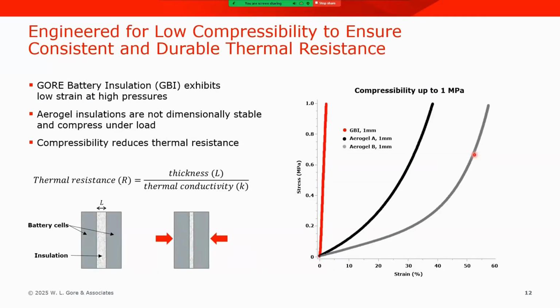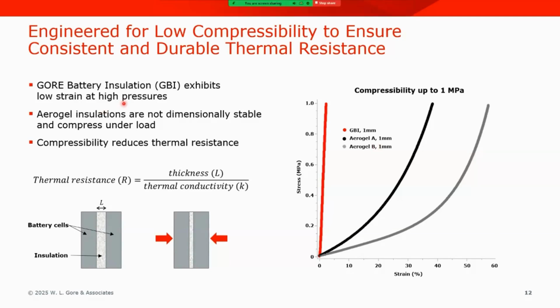So let's think a little bit about compressibility. And first of all, how we measure compressibility, and secondly, its impact on the thermal barrier performance. As I've mentioned, GORE battery insulation exhibits very low strain, even at high pressures. And that can be seen here in the stress strain plot on the right side. In this case, we're comparing GORE battery insulation, which is the red line, to two different commercial aerogel pads, which are marketed as battery insulations. We're just going to refer to them as Aerogel A and Aerogel B. And all of these materials are measured with an initial thickness of 1 millimeter.